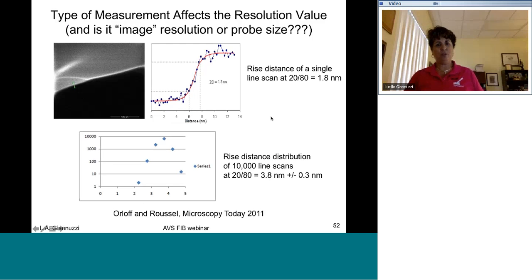So the other thing that you should be aware of is how, again, resolution is measured. And typically what you want to do is measure the so-called rise distance of a line scan. And typically you want to do this over thousands of line scans. Here, if we just take the rise distance, this is just measuring the contrast across a particular line. And for the rise distance, you also have to ask, what is the interval that they're using? So if I use 20/80, 20% and 80% of the rise, and I measure that, that distance is 1.8. If I say I'm going to use 35/65, 35/65 is going to make this number smaller, okay?